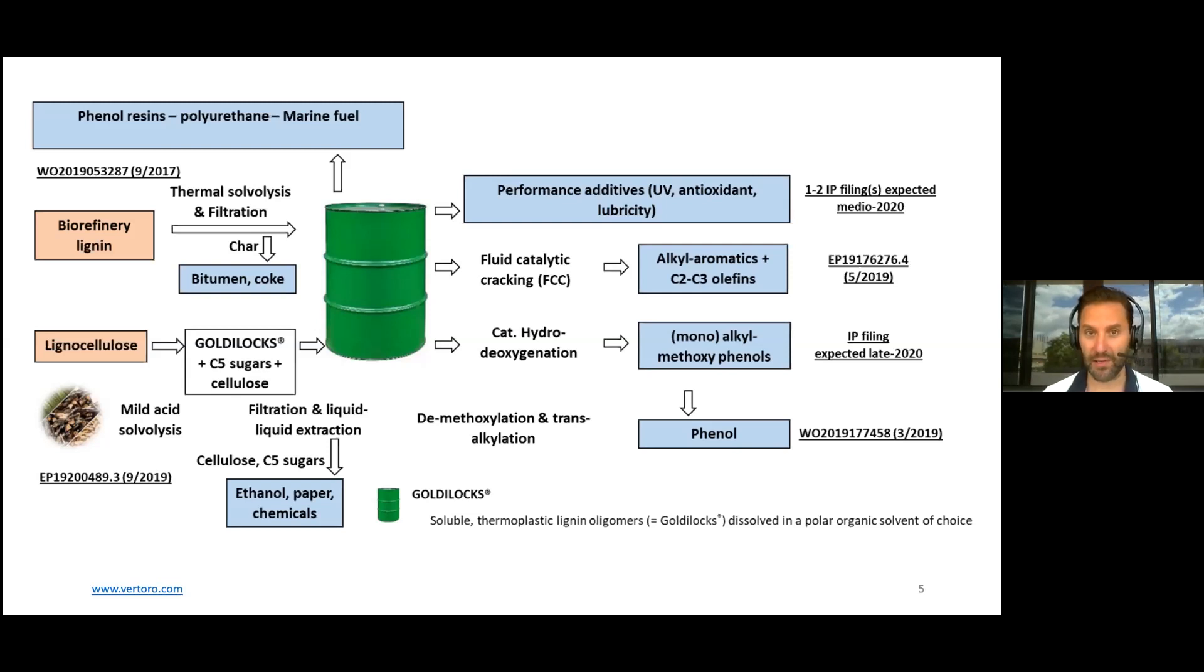The C5 sugars, we can either leave in the product oil or take them out. For the marine fuel application, it's not a problem if the sugars are still in. For polyurethane, we're getting feedback from the industry that too many sugars are a problem. So we developed a ethyl acetate water extraction method to get the C5 sugars out of the oil phase and into a water phase.